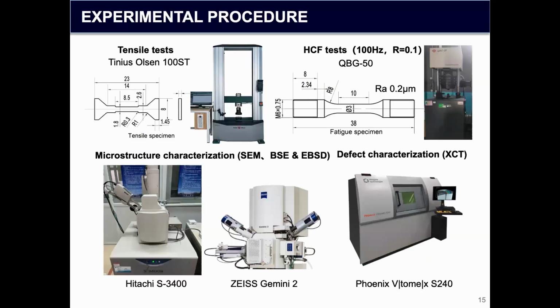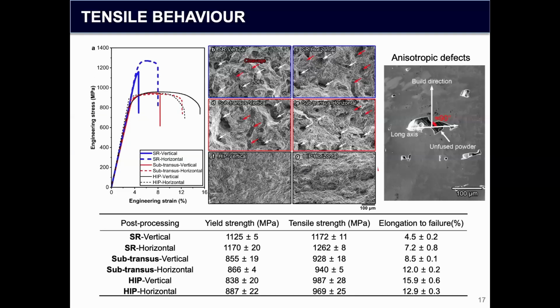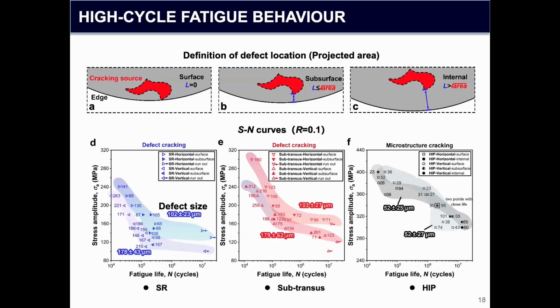And this is the experimental equipment we are using and the specimens of the tensile test and the high cycle fatigue test. So let's see some results from the test. On the left-hand side figure, we can find the SR state has the highest strength, but the material becomes very brittle. For sub-transus and HIP states, we have a similar yield strength, but the ductility of the material becomes better than the previous one. And this is how we define the defect location and the area of the defect, because we would like to use these kinds of parameters in our models.